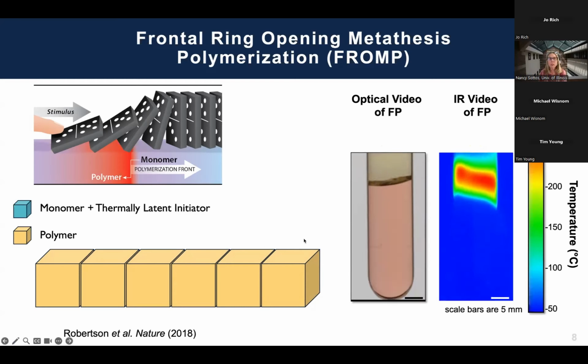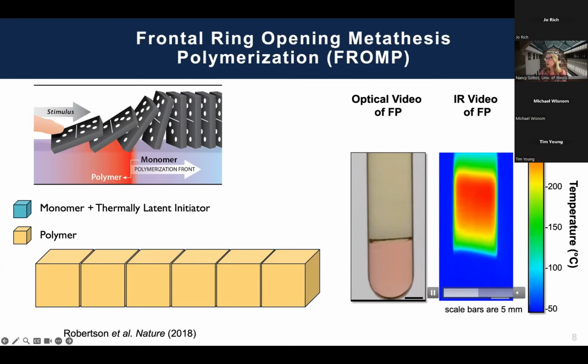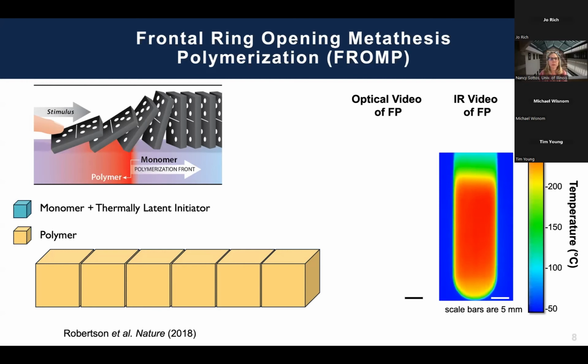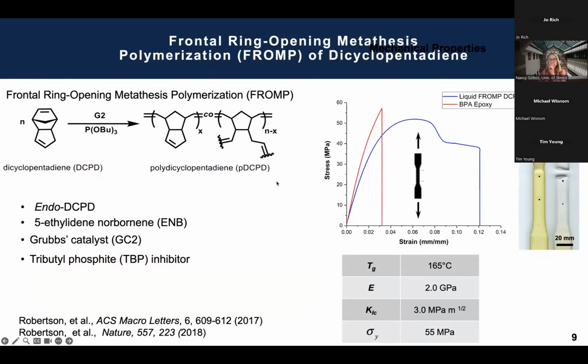In a test tube, it looks like the images you see on the right. The heat has been applied at the top, there's a uniform propagating front, and on the right you see the IR video, and you can see there's quite a bit of heat generated, and you can see it diffusing forward and moving with the front as it goes down, and then basically you convert to 100% polymer. The chemistry that we are using is not an epoxy.